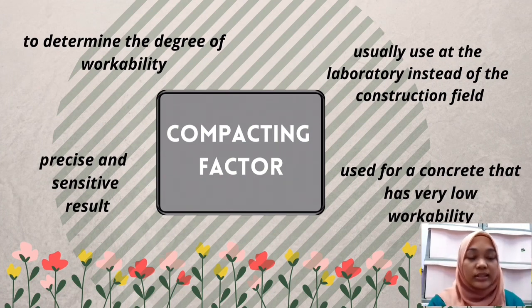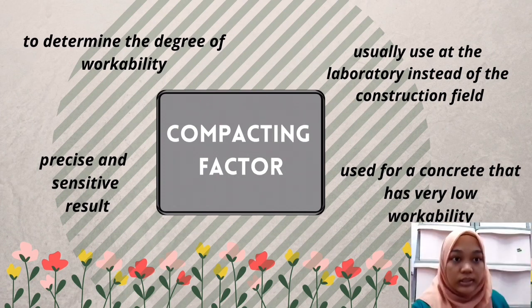Next, the test used in this research is the compacting factor test. Compared to the slump test, it determines the degree of workability of the fresh concrete. It is usually used in the laboratory, but it can also be used at the construction site directly. However, it is very rare to use at site work because it needs a large device. The advantage of this test is that it is more precise and sensitive than the slump test, and it is usually used for fresh concrete that has very low workability.